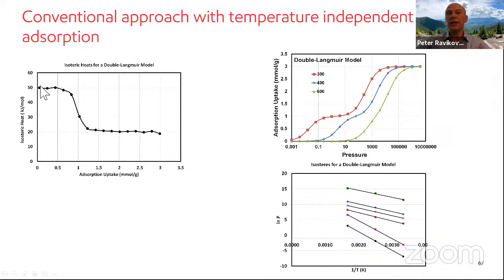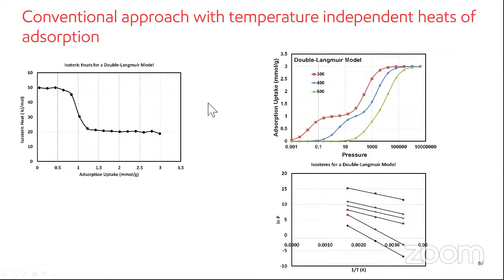So if you have something like a two-site adsorbent, and adsorption is represented by a double Langmuir model, you have a perfectly linear isostere of adsorption. But there is no room in this model to have a temperature dependence of the heat of adsorption. It's just not there, right? So in order to have the temperature dependence, you need to have not only different adsorption sites, you need to have a redistribution of molecules between these two sites occurring when you change temperature. Does that answer the question?